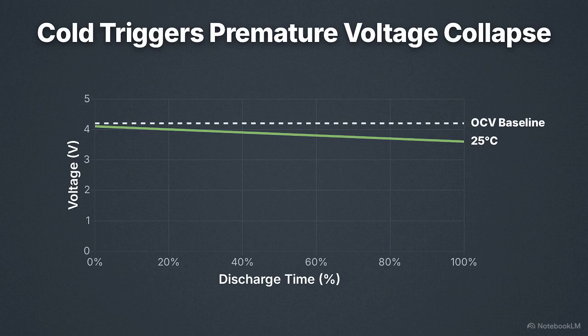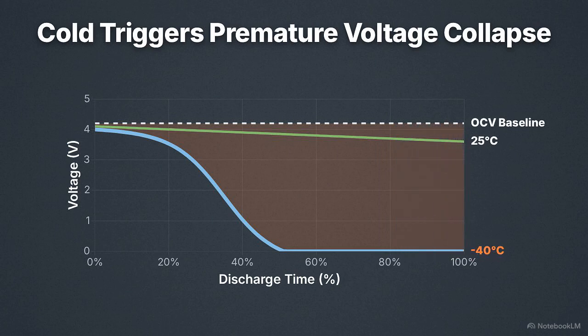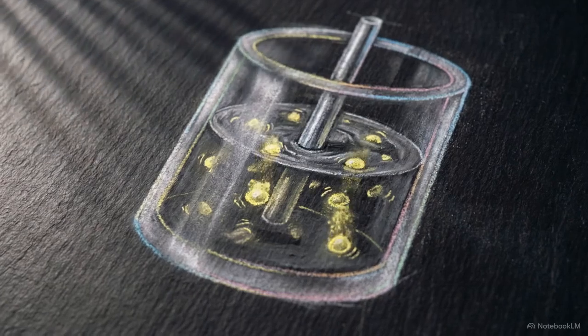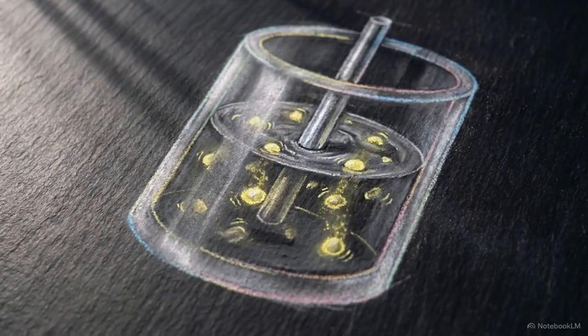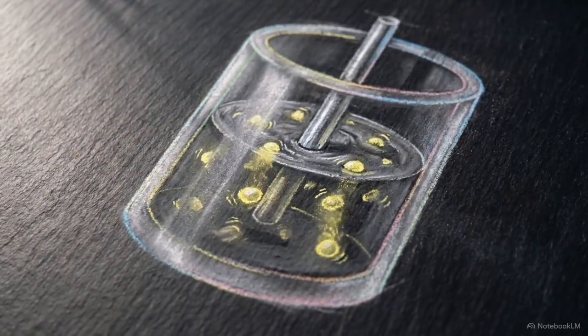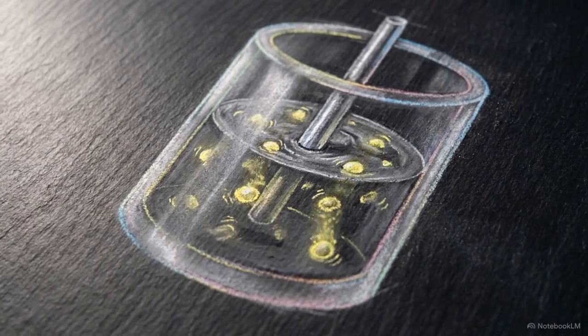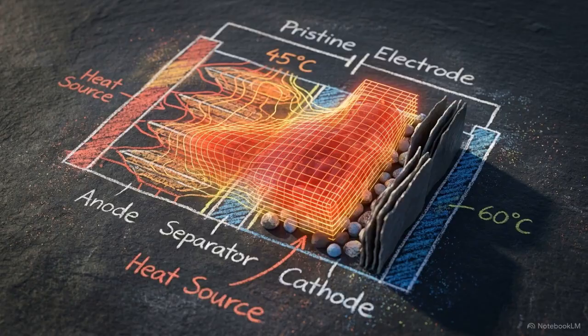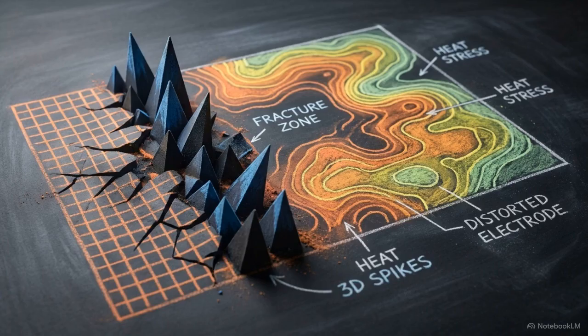This graph shows what happens when we drop the temperature. The 25-degree ideal remains flat, but the -40-degree operational reality plunges prematurely under load. The theoretical energy remains present in the cell. The collapse happens because the battery cannot extract that energy fast enough to sustain the load. To fix this, we need to map the internal energies of the electrodes under perfect conditions, and then pinpoint exactly what breaks when the system is put to work.